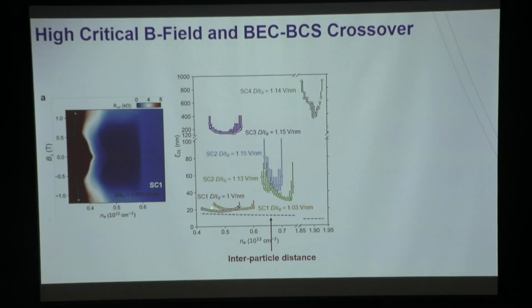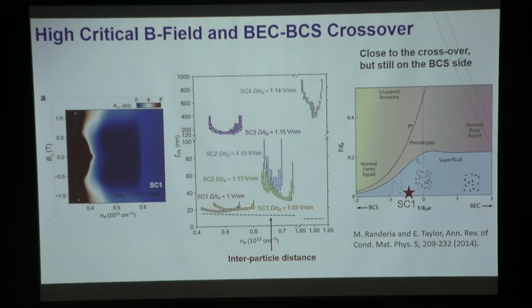And you find that in SC1, they are already pretty close to each other. So this is telling us that we're close to the so-called BEC to BCS crossover, although we're safely in the BCS side, but we're very close to it. And this may be suggesting that we have a strongly coupled superconductor.